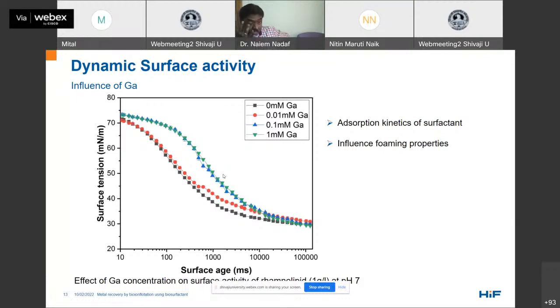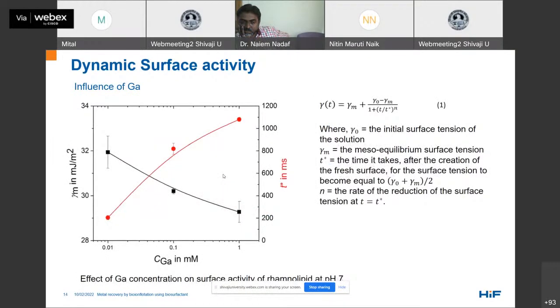And this surface activity can again be explained very well with the help of an empirical relation, which is usually derived from the Rosen equation, which can be seen here. It helps us to derive the values for the meso-equilibrium surface tension, which is gamma m, and t star as a function of gallium concentration.